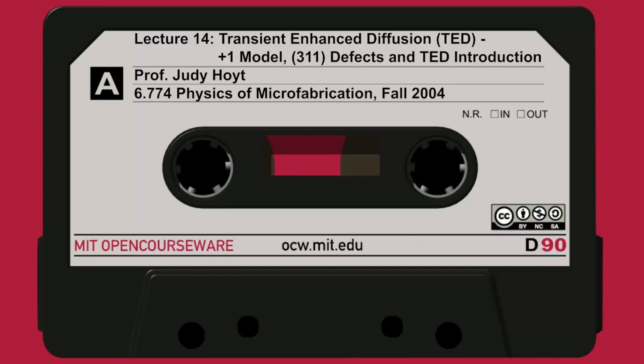These excess interstitials all get together and cluster into these 311s very quickly, in less than a tenth of a second, and they dissolve very slowly, and that dissolving process gives rise to TED. And we have a simple model for TED that can explain the time, the temperature, the dose, and roughly the energy dependence of TED.